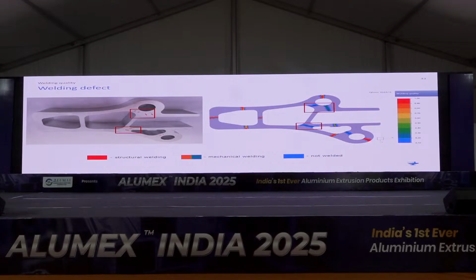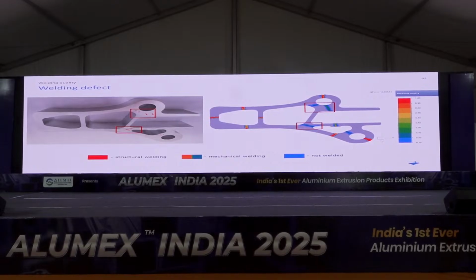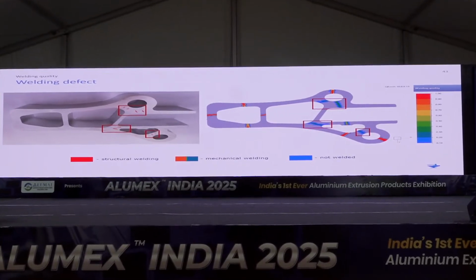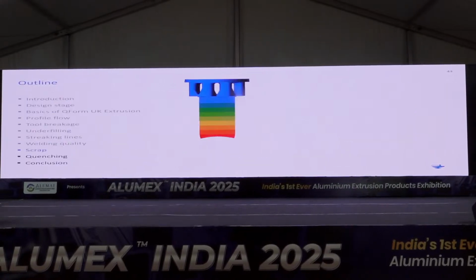Another example, just to make it faster. Here you can see the area where we can see a visible interface between two different streams, so basically between two different ports that form this profile and form this weld. And this area is very bad. This is what we really can call mechanical welding. And here you can see all the welds which don't have a good quality were marked, and it has a very good correlation with the software.